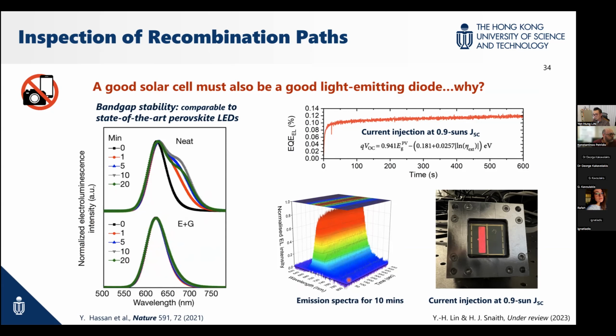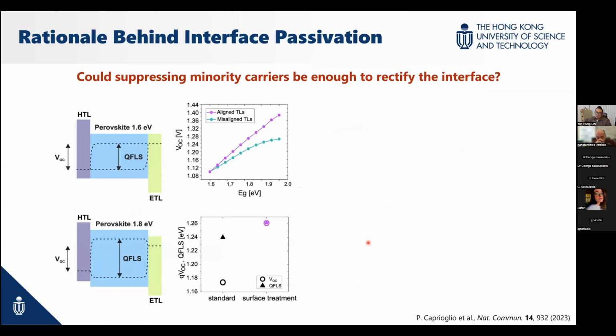and 20 minutes. But something surprising to us is that we have a thick film beyond 500 nanometer, and we only preserve the surface. The halide segregation doesn't exist in this circumstance. Of course, this is encouraging, but it might indicate that the halide segregation actually all comes from the surface. So the surface is important.